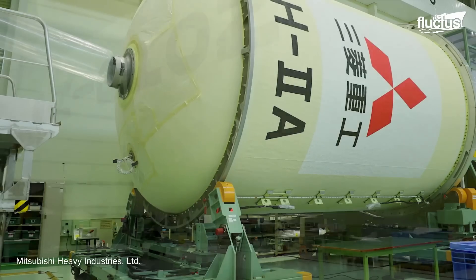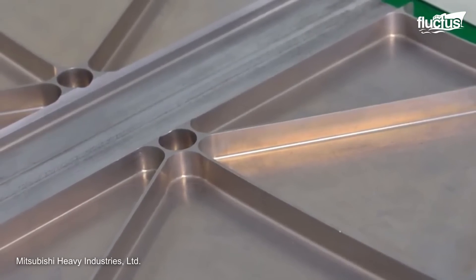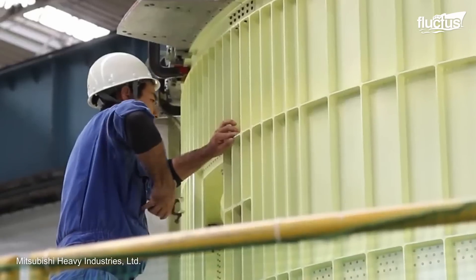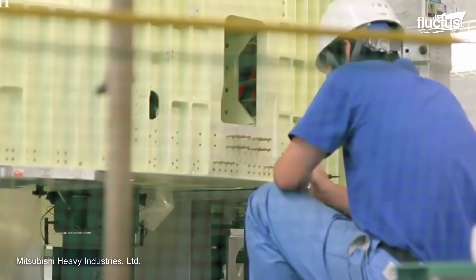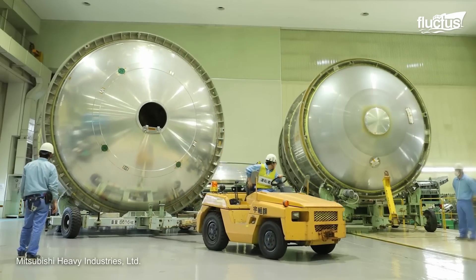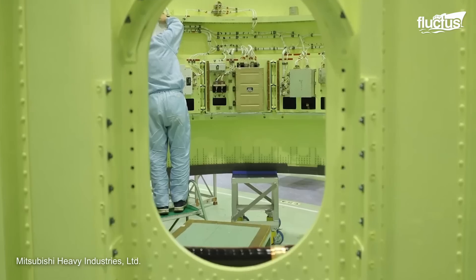This is done to ensure the material is capable of resisting the enormous loads and vibrations that can be generated by a rocket. The isogrid panels are filled with a low-melting wax to prepare them for the rolling forming process, allowing the bending force to be distributed throughout the structure during rolling, making it stable and reducing the possibility of buckling of the ribs. After rolling, the wax is melted at temperatures beyond 140 degrees Fahrenheit and is washed away by inserting the panels into a water tank.